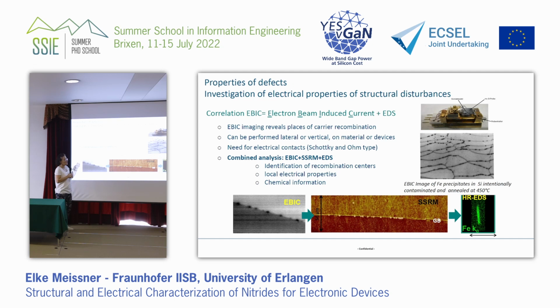So what you do in EBIC, you measure places for electrical recombination. You put a potential on your material and you divide the carriers, the holes and the electrons, in an electric field. Then you create excess carriers with the electron beam. And then inside your field, the excess carriers recombine or not. And they recombine, like with optical recombination, at places where you have dislocations.